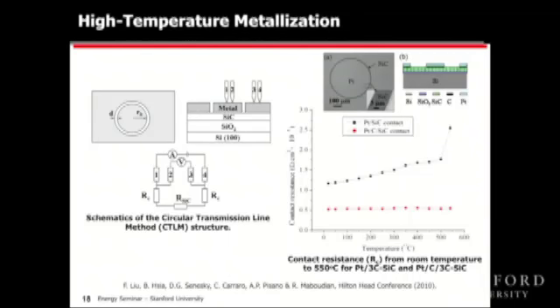However, if you position a graphite layer in between the platinum and the silicon carbide, you can inhibit this chemical response. So with graphene, we can graphitize the silicon carbide, put platinum on top, and when you heat it up from room temperature up to 600 degrees C, you get a stable contact resistance. So there's no electrical change in the material from room temperature up to 600 degrees C.